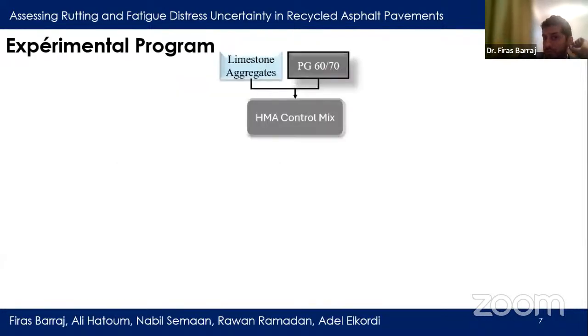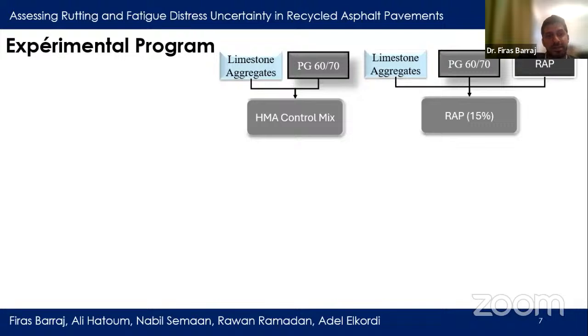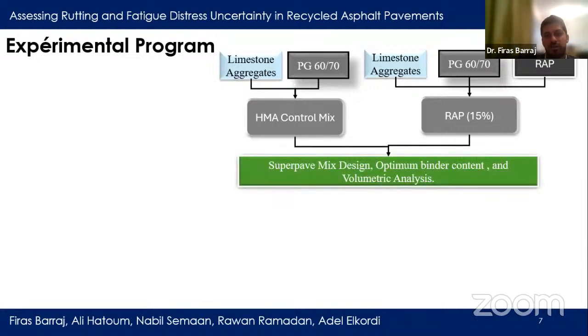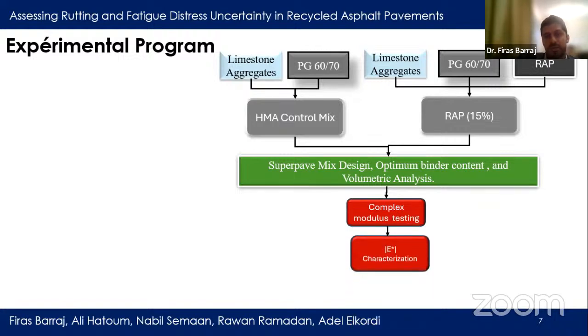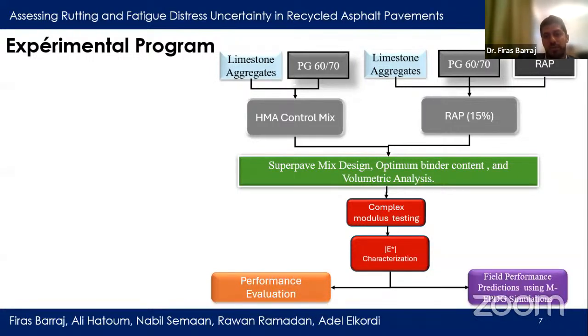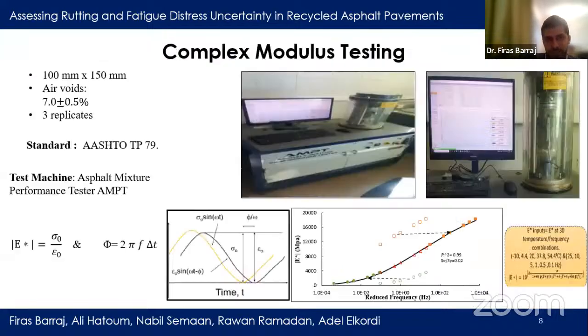In the experimental program, two different asphalt concrete mixes were prepared, a control mix representing the standard HMA in addition to a RAP mixture incorporating 15% of RAP. The mix design was performed according to the Superpave design method with adherence to its volumetric criteria. Complex modulus testing was conducted to characterize the viscoelastic properties and performance of the asphalt concrete mix, and finally, the field performance of the pavement structure incorporating the analyzed AC mixes was assessed using MEPDG simulation.